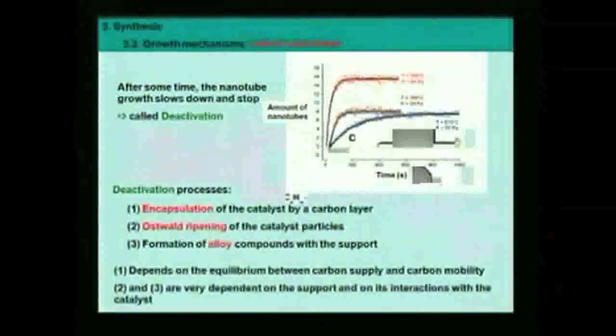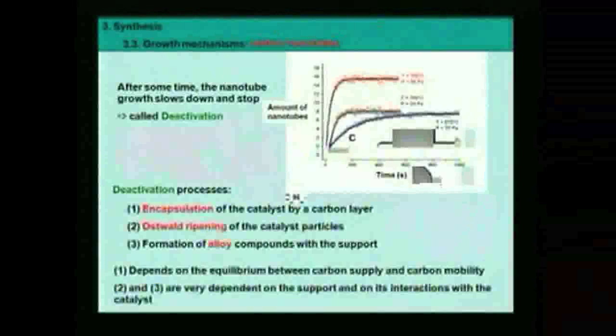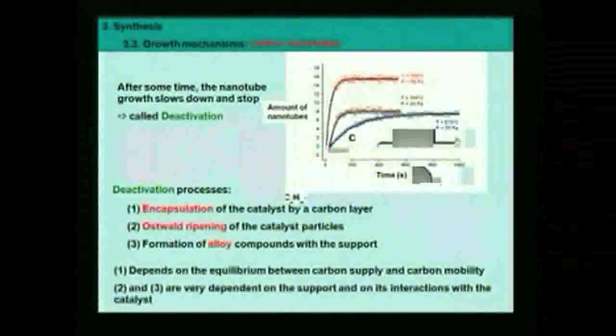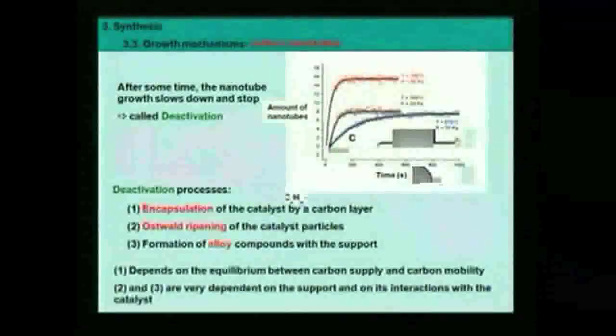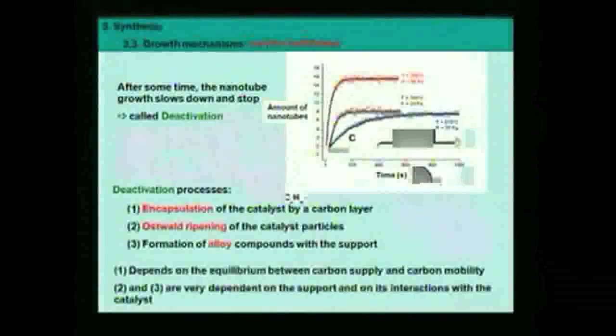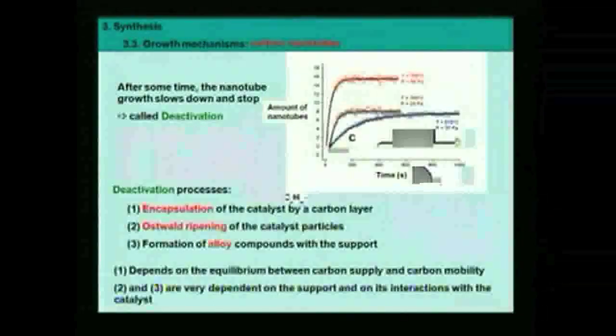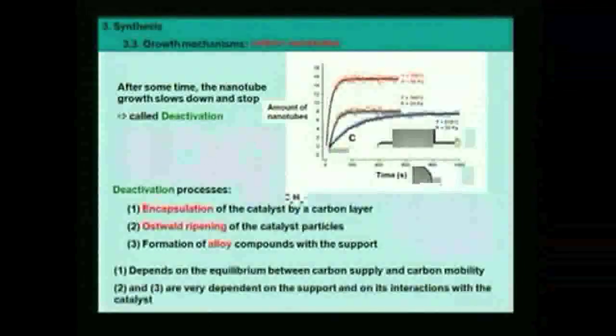Just to show you that deactivation is real, this is a plot of the amount of nanotubes formed as a function of time, for 3 different growth conditions. And you observe that at the end, the amount of nanotubes stagnates. You have no more growth. We have done nothing. It was just natural. Deactivation occurred by itself. It's self-deactivated. Depending on the conditions, you can have more nanotubes or less, but whatever the conditions, there is always deactivation at some point, for those reasons.